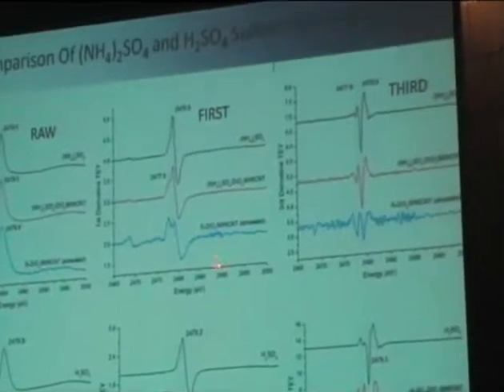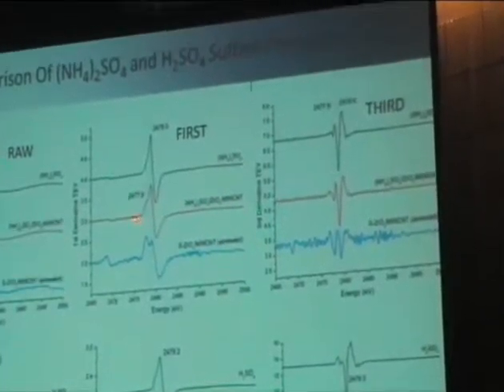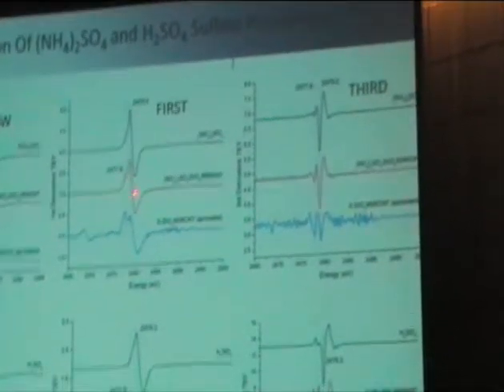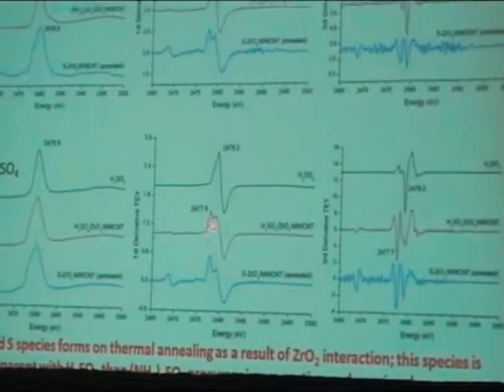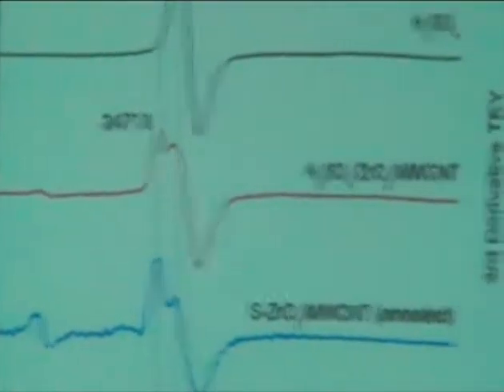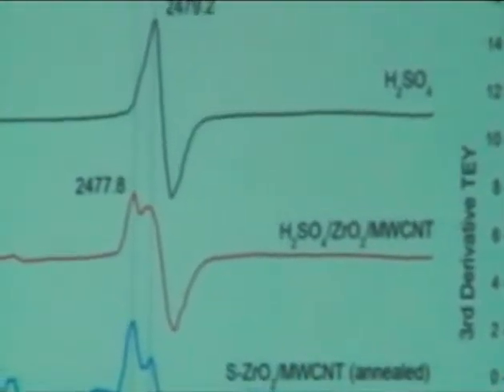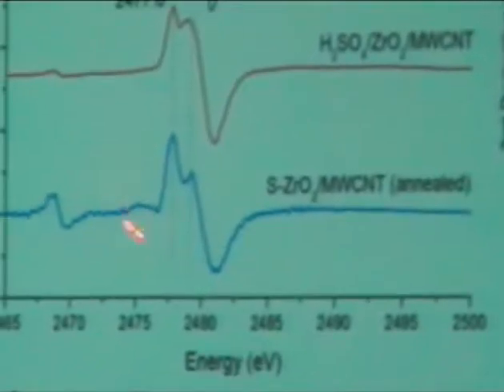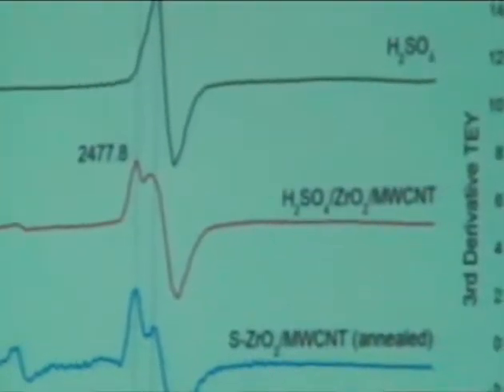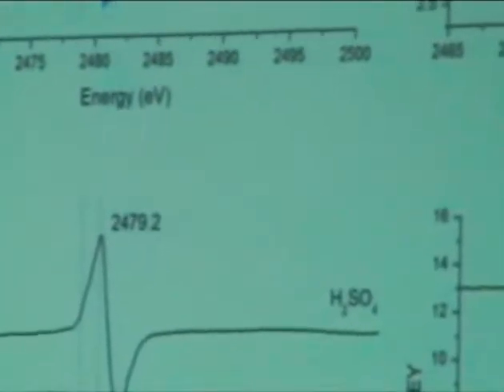What I want to draw your attention to is that if you, instead of using the ammonium sulfate, you use sulfuric acid, that second peak is much more evident right after impregnation. But after the calcining, essentially you get the same final result when you have ammonium sulfate or sulfuric acid. So one possibility is that that second peak might have some association with protons, more available when we impregnate with sulfuric acid than when we do with ammonium sulfate. That's at least a working hypothesis.